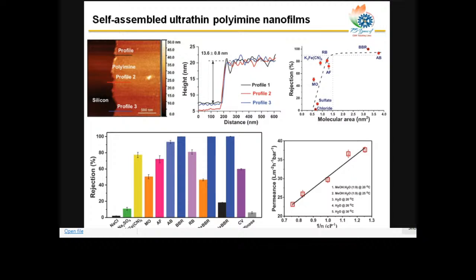On the left bottom, you can see the rejection of many different ions and small molecules, like sodium chloride, sulfate, potassium ferricyanide, methyl orange, acid fuchsin, azobenzene. All these molecules, you can see depending on their molecular size, you can have their separation. Something like methyl orange and brilliant blue R, a mixture of these two molecules will also help you to get the small molecule going through the membrane, while the bigger molecule will be retained on the top part of the membrane. So you can actually fractionate them depending on the molecular size of the model molecules we chose here.